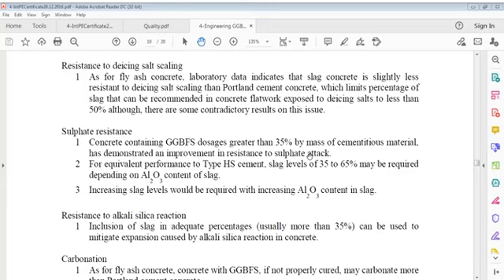Resistance to de-icing salt scaling. As for fly ash concrete, laboratory data indicates that slag concrete is slightly less resistant to de-icing salt scaling than Portland cement concrete, which limits the percentage of slag that can be recommended in concrete flat work exposed to de-icing salt to less than 50%, although there are some contradictory results on this.